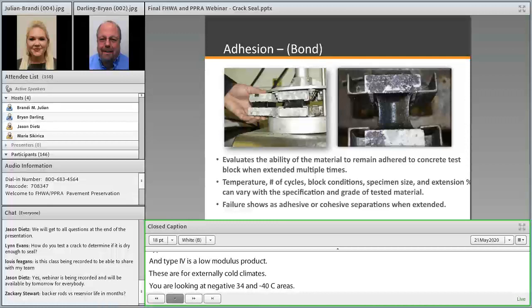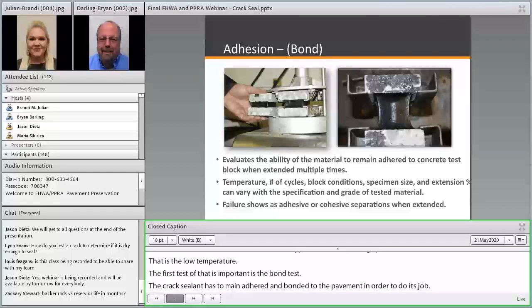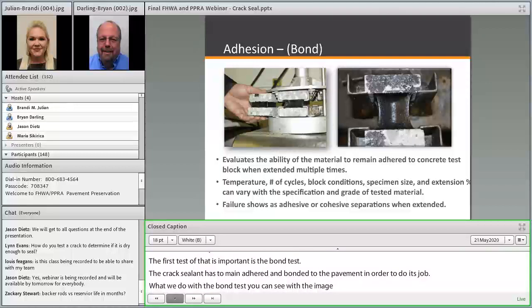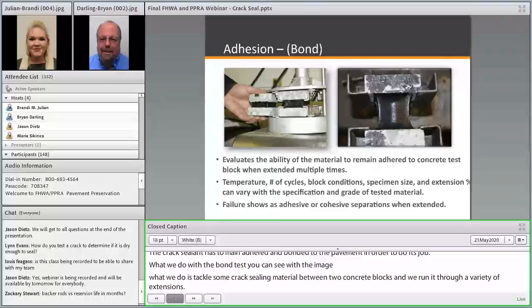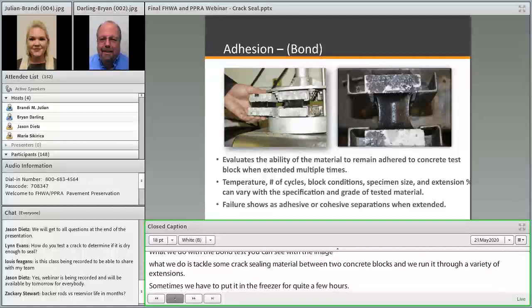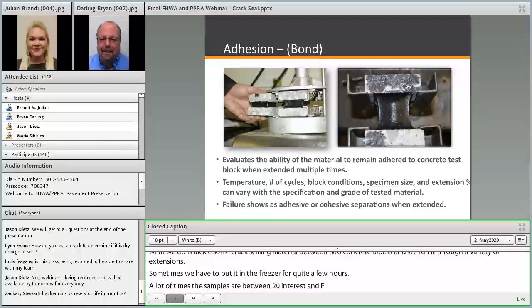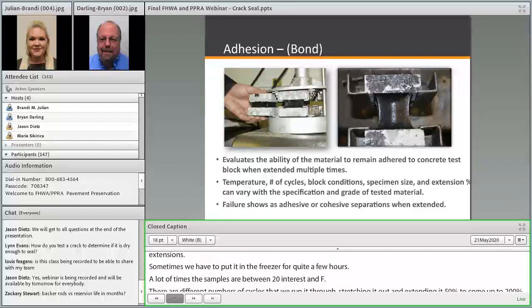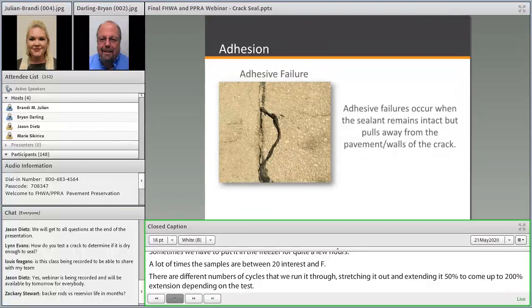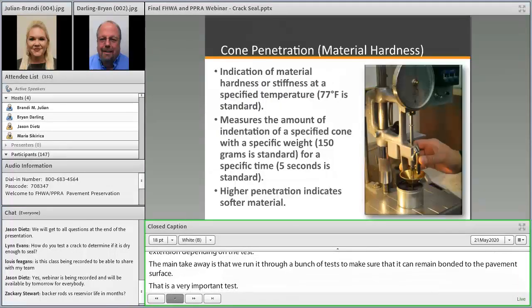And the first test that's really important is the bond test. Adhesion is important. Crack sealant has to remain adhered and bonded to the pavement in order to do its job. So what we do is a bond test. You can see from this image what we do is cast some crack sealing material between two concrete blocks, and we run it through a variety of extensions. Sometimes we have to put it in the freezer for quite a few hours. A lot of times the samples are between negative 20F and 20F. There's different numbers of cycles that we run it through, stretching it out, extending it, 50% up to 200% extension, depending on the test. But the main takeaway is we run it through a lot of tests to make sure it can remain bonded to the pavement surface. So that's a very important test. Because in the field, if you don't have good bond, you get adhesive failure, as you can see here in this image, and the sealant will pull right out of the crack.